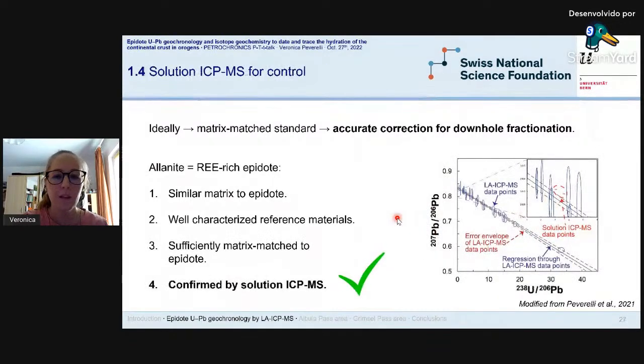This entails that epidote and allanite are sufficiently matrix matched, meaning that we will calculate accurate ages from accurate isotope ratios. Of course, we wanted to double check the calibration of our protocol, and we did so by plotting the same isotope ratios measured by an independent technique, which for us is solution ICP-MS. And we plotted them in a Tera-Wasserburg diagram along with LA-ICP-MS data points. So LA-ICP-MS data points are the blue ellipses, and these red circle dots are the solution ICP-MS data points. And as you can see, the data sets acquired by the two independent techniques are nicely consistent, meaning that our protocol is well calibrated.